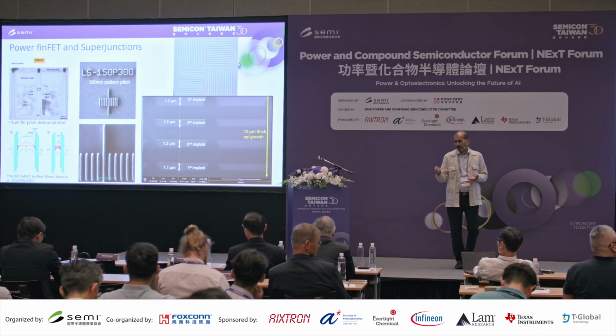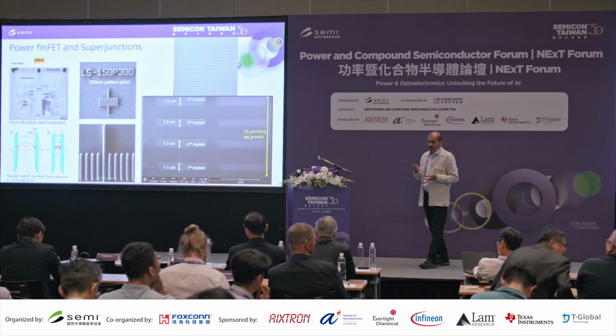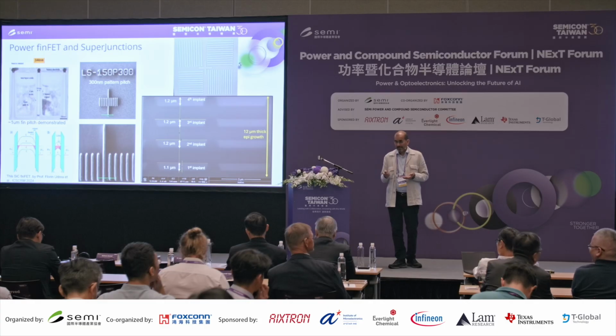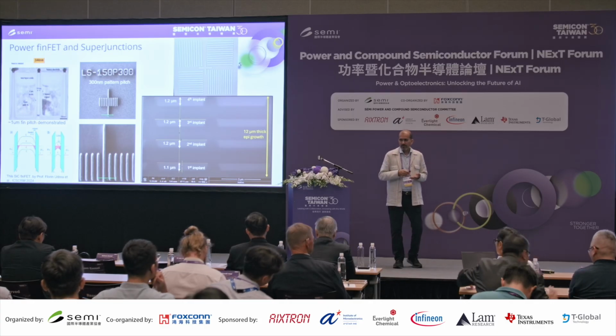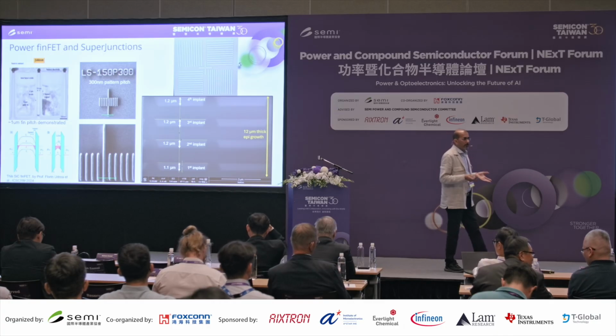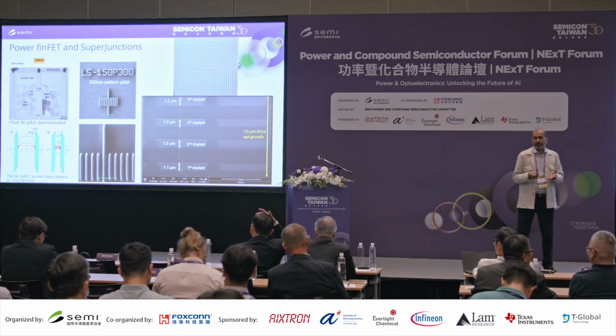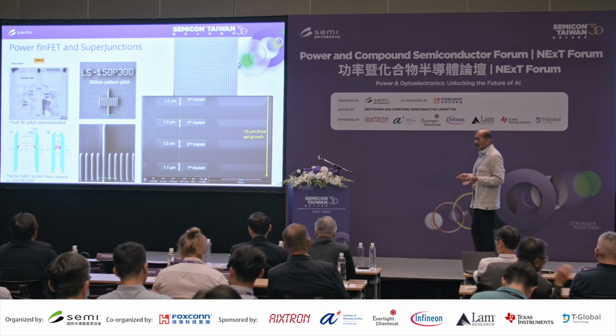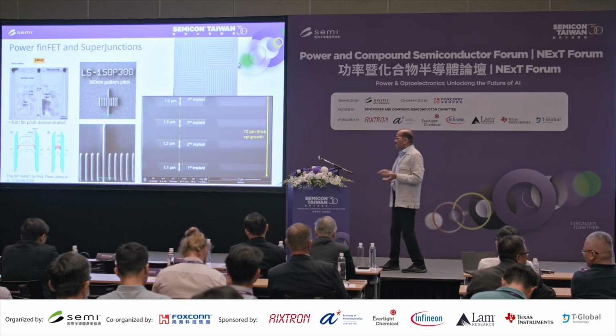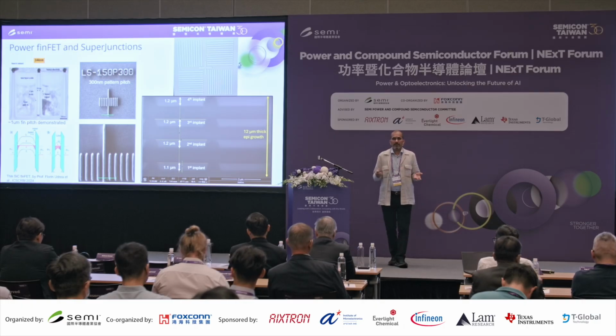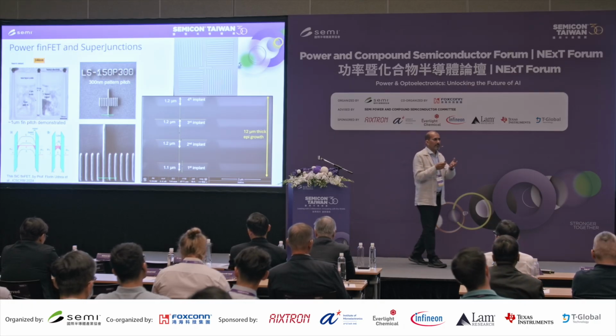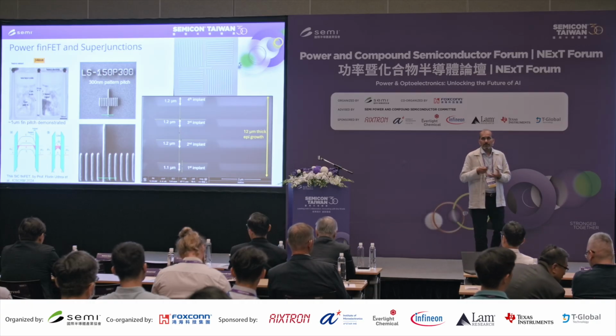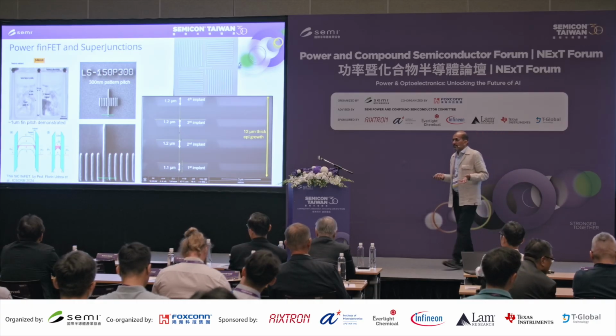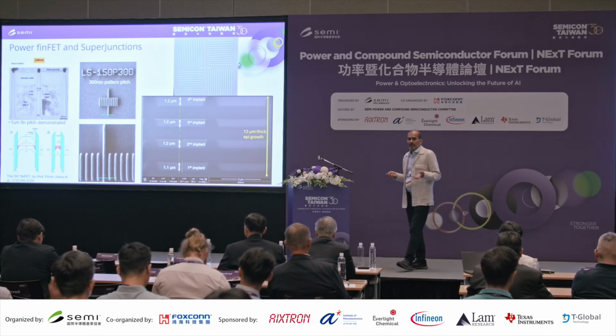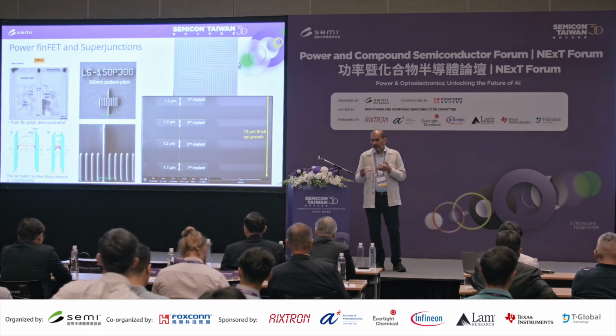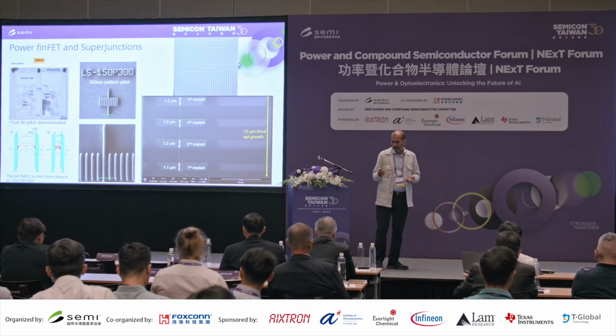We have done the column formation for a superjunction using implant epitaxy, and for that we developed an alignment mark. The problem of industry today is, if you have an alignment mark which has a topography in silicon carbide, you just cannot keep that alignment mark safe during the epitaxy. Silicon carbide epitaxy will make it distorted, and this alignment mark will not work. Other material does not survive at epitaxy temperature, which is 1600 plus degrees centigrade, right? So how to make this alignment mark is really a key innovation here, and we have done it.